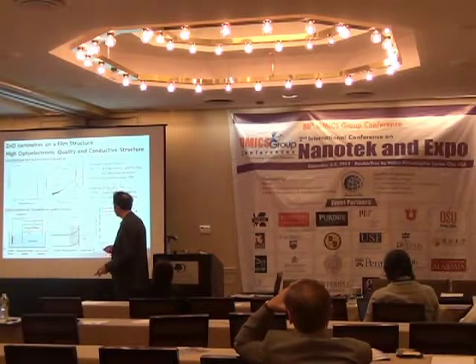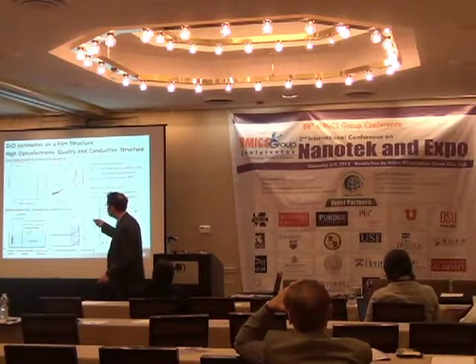Okay, so the next point was to check the optoelectronic quality of that material. We did that by low temperature photoluminescence and observed the free exciton emission here in this region. So this indicates a good material as well.